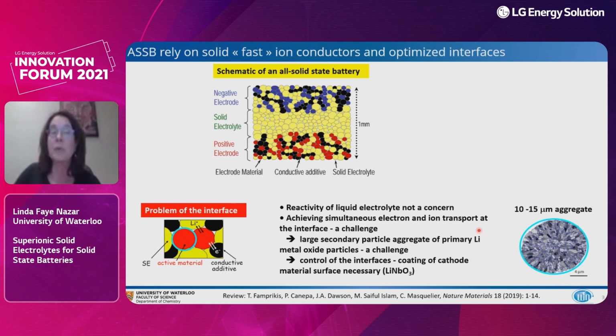And in order to basically suppress reactions of the electrolyte with that NMC material, they have to be coated with something like lithium niobate, and I'll address that in the latter portion of the talk. So controlling the interfaces, especially at the positive electrode, is really problematic. Of course, it's problematic at the negative electrode as well.